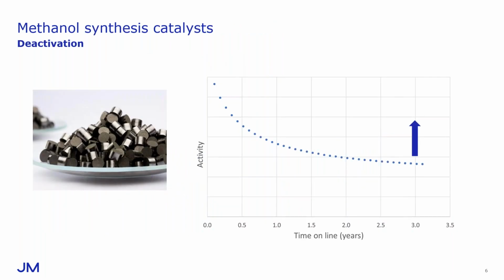And this highlights that even with mature technology areas such as this, it is still possible to make step-out improvements. So how was this achieved? In the past, the focus has tended to be on improving the initial activity of the catalyst and then assume that any activity advantage that's obtained will be subsequently retained over the useful operating life of the charge. However, as you can see in this indicative activity versus time plot, methanol synthesis catalysts tend to lose a large proportion of their activity with time online.